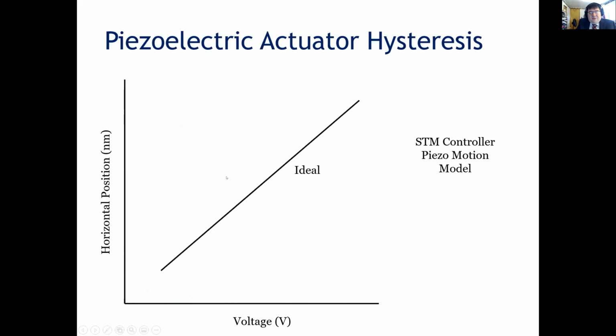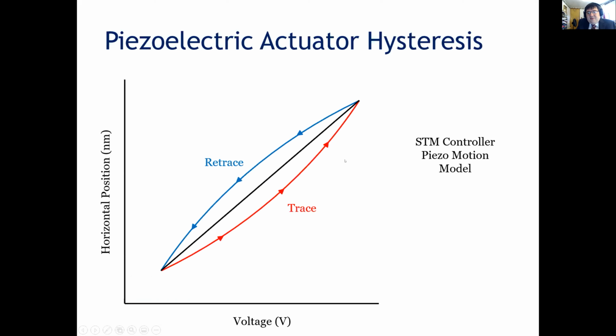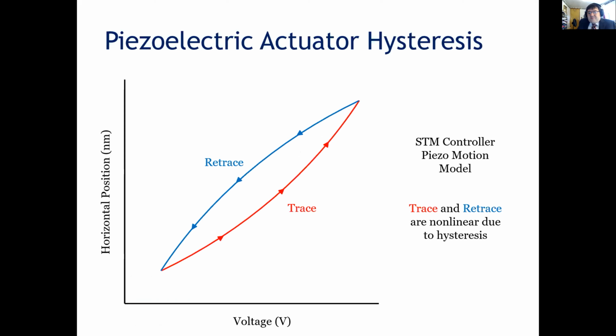There are some problems with this. We control the scanning probe microscope tip with piezoelectric actuators. The STM controller has a model for that that says when I apply a voltage, I get constant motion per volt applied. So this is the model it has. But in practice, due to piezoelectric actuator hysteresis, on the trace it does not follow this line. And on the retrace, it doesn't even follow the same line. It follows a completely different line. And so we need to take account of that for our distortion.